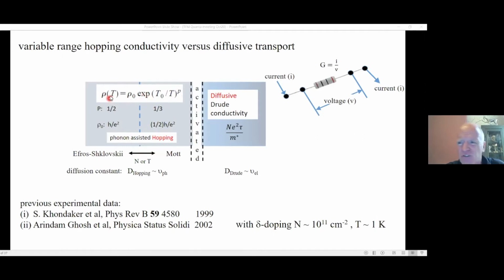So the resistivity at some temperature T is a prefactor ρ0, which is the high temperature limit, and then an exponential with some characteristic T0. T is the variable temperature, and P is a power. Now, if we were in the activated regime, this power P would be just 1, and k T0 would be equivalent to an activation energy. But what we see in this hopping regime is that the system behaves in this way. If the power P is a third, we're in the so-called Mott hopping regime. And the prefactor, which is quantized, is a half of h over e squared.